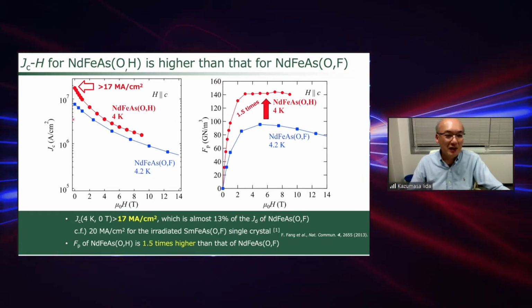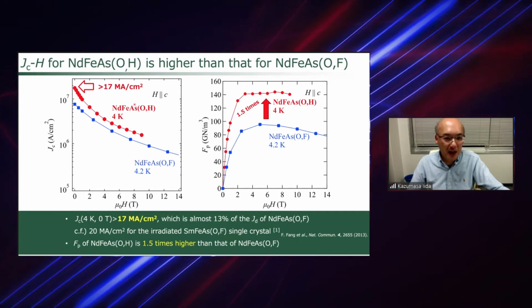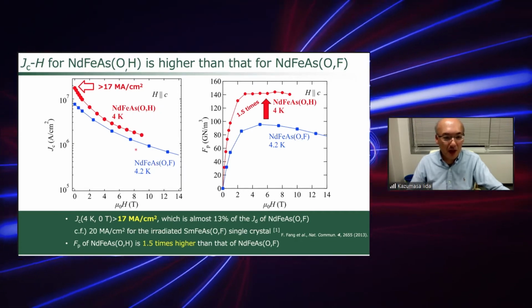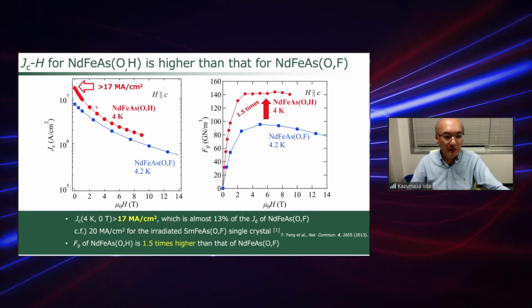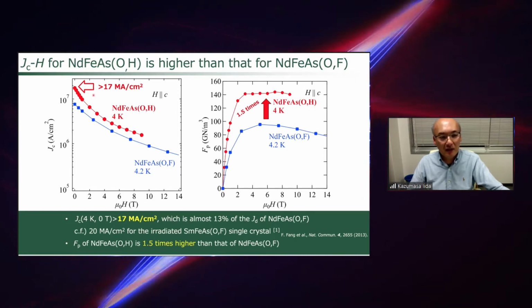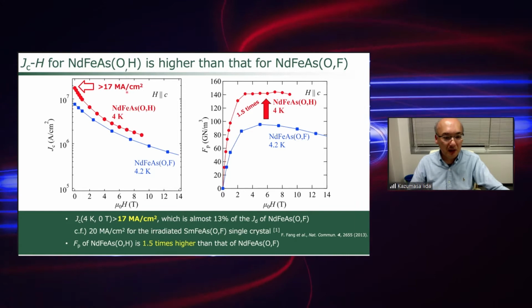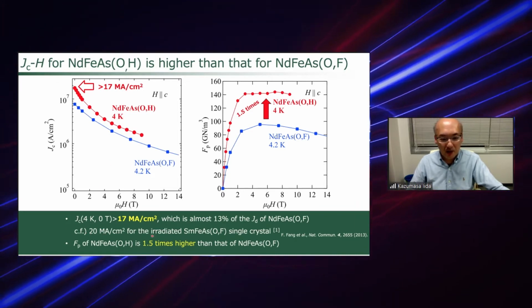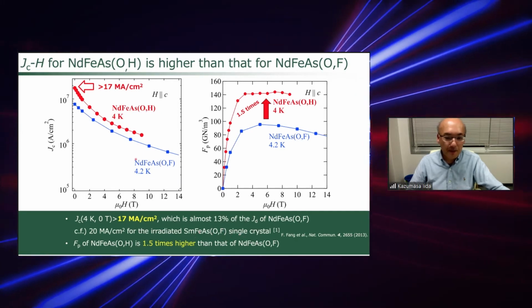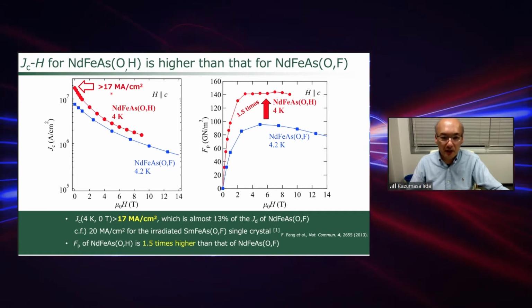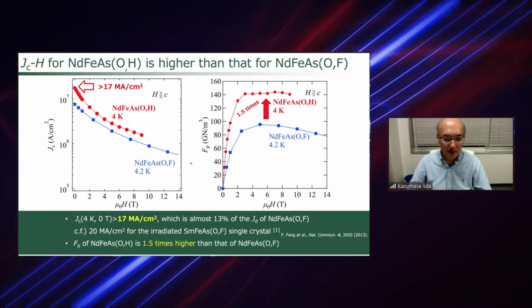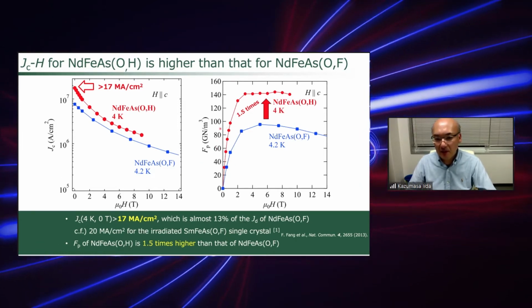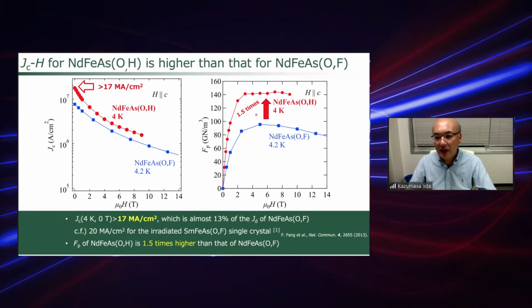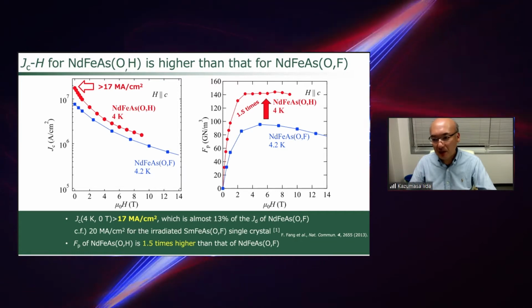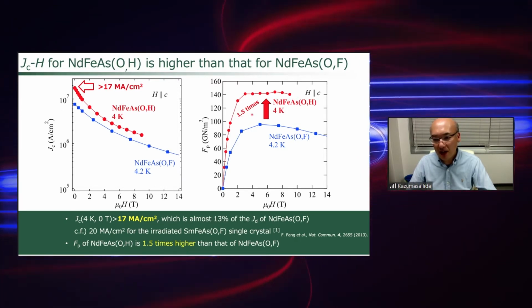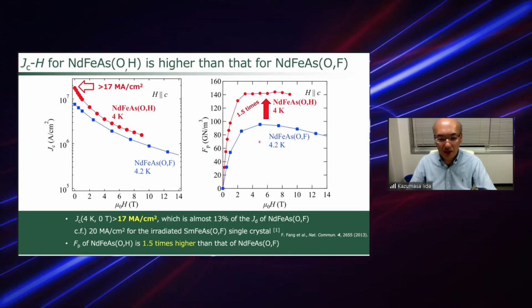Okay, so this is the field dependence of the critical current density of the hydrogen-doped samples and our best performing fluorine-doped samples, measured at 4.2 Kelvin. And very surprisingly, we obtained a very high critical current density over 17 mega-ampere per square centimeter, which is almost comparable to the heavy ion irradiated SmFeAs(O,F) single crystal. And this value is almost 13% of the depairing current density of the fluorine-doped 1111 films. The right-hand side is the pinning force density as a function of the applied magnetic field. Our pinning force density of the hydrogen-doped samples is almost 1.5 times higher than the fluorine-doped 1111 films.